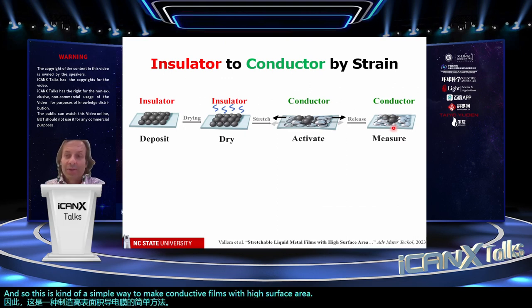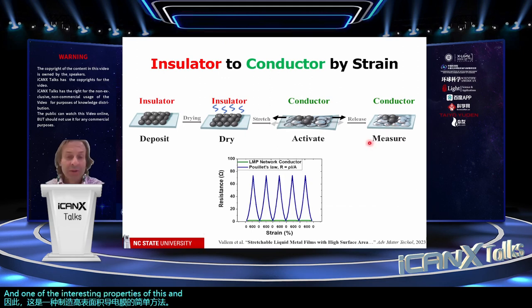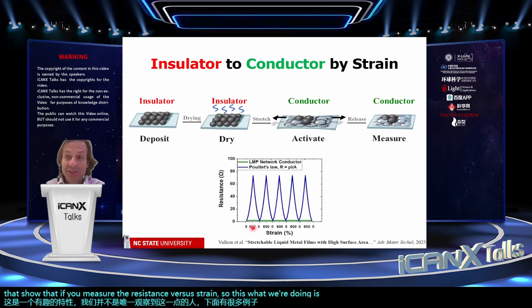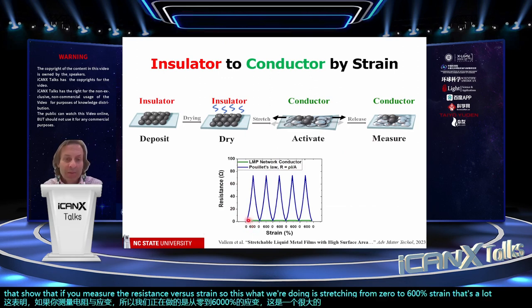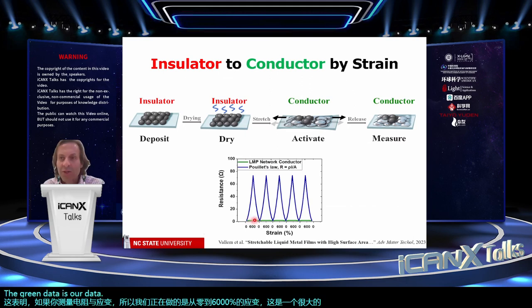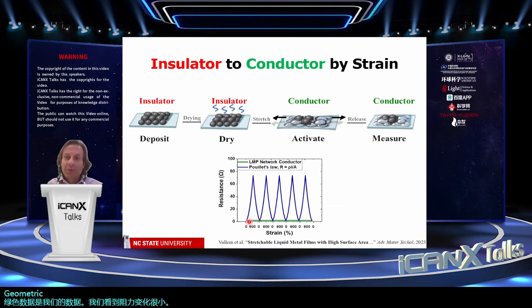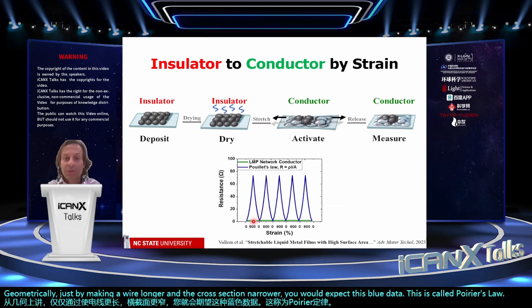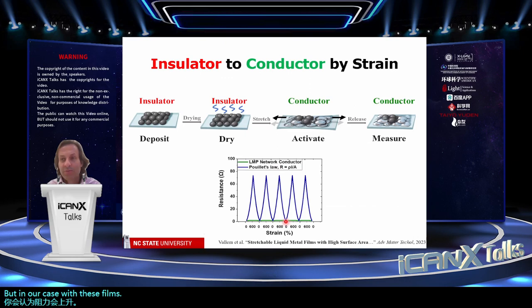One of the interesting properties of this, and we're not the only ones to have observed it, there are quite a few examples now in the literature, is if you measure the resistance versus strain. What we're doing is stretching from 0 to 600% strain. That's a lot of strain. The green data is our data. We see very little change in resistance. Geometrically, just by making a wire longer and the cross-section narrower, you would expect this blue data. This is called Pouillet's law, and you would expect the resistance to go way up. But in our case with these films, the resistance barely changes. This is something maybe we can talk about during the Q&A, because it's an open question as to why this works.